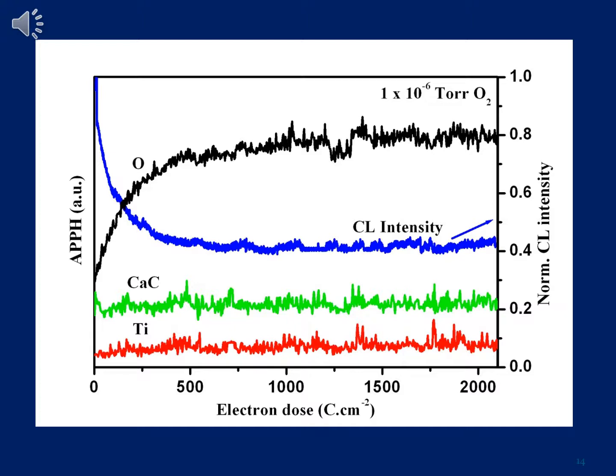At the same time, we also realize that the CL intensity is decreasing rapidly to about 40% of intensity and begins to stabilize around 500 electron doses as well. Now, this is a clear indication that there is a new species which has been formed on the surface, which is quenching my luminescence intensity.